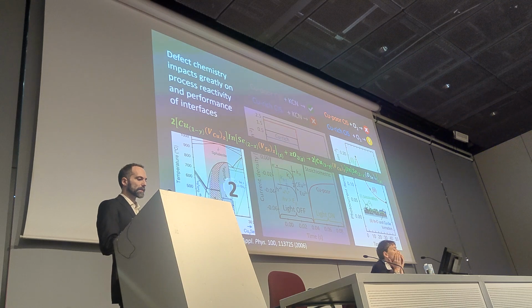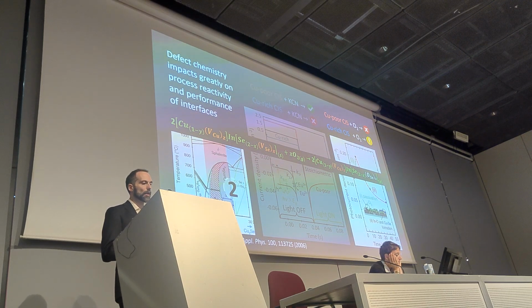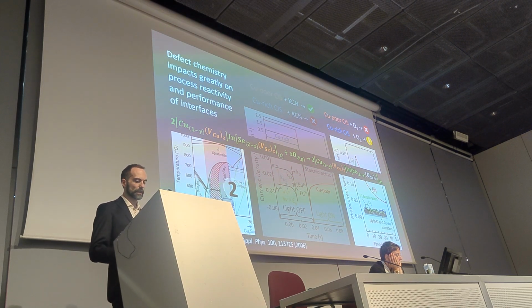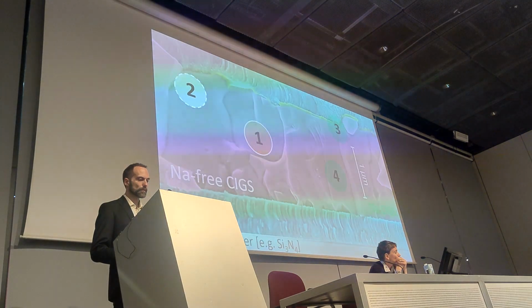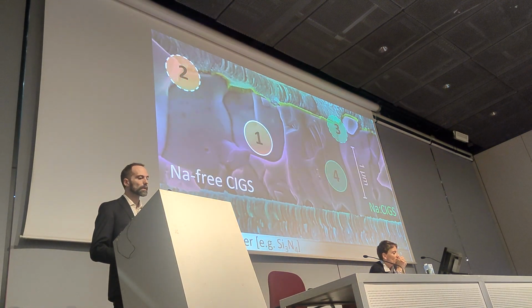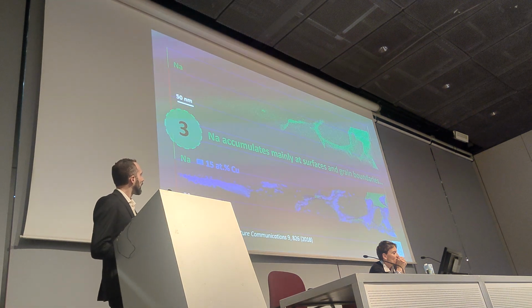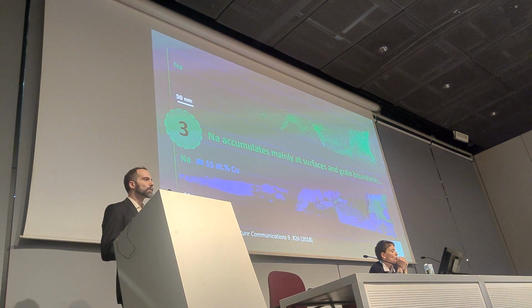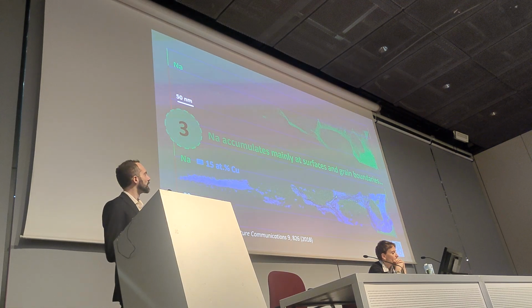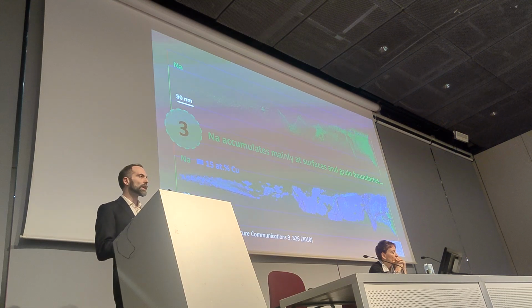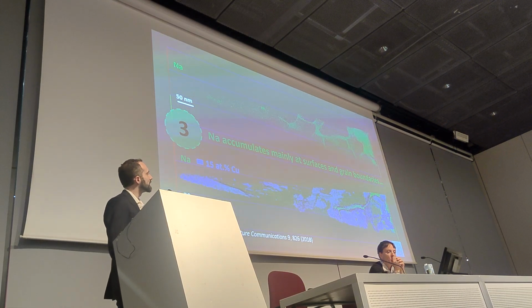So what we learn from this is defect chemistry impacts greatly on process reactivity and performance of interfaces. So let's now look into what sodium does at interfaces. And I'm showing you here an atom probe tomography 3D map reconstruction of the location of sodium atoms in a CIGS film. What we observe here, there is a strong accumulation of sodium at specific locations. What you see there, they are basically extended defects, grain boundaries and surfaces.